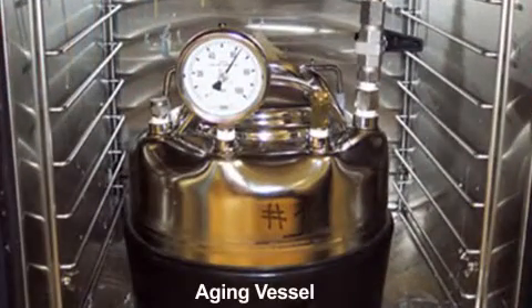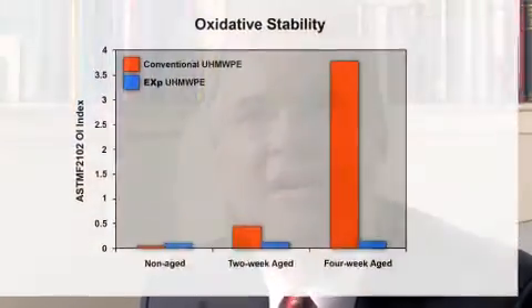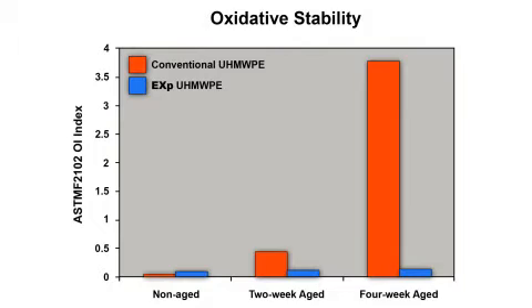There are three key features of the EXP liner technology that I'm now going to go through. The first of these is oxidative stability. We've looked at oxidative stability two ways. First, we put polyethylene liners that were blended with vitamin E using the EXP technology into an accelerated aging bomb, and we accelerated aged them for a month. When we looked at the EXP liners and compared them with the undoped materials or the unblended materials, we found that the vitamin E containing materials had negligible oxidation, whereas the conventional polyethylenes oxidized.